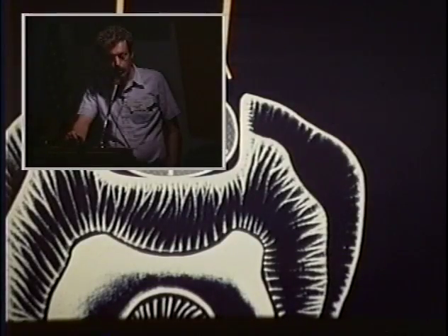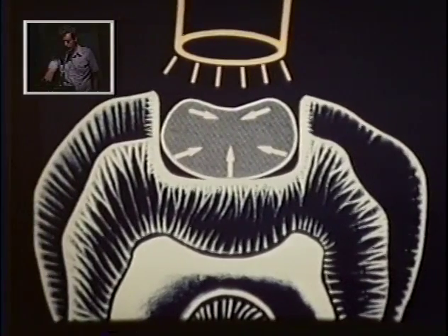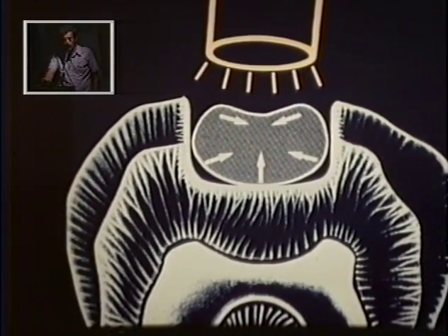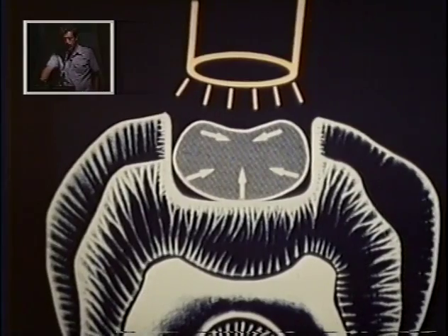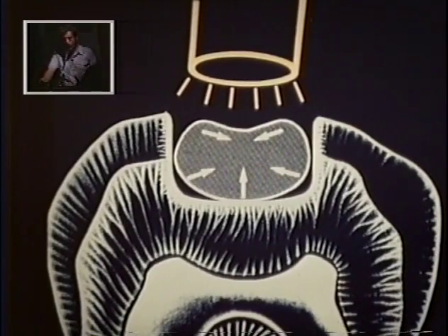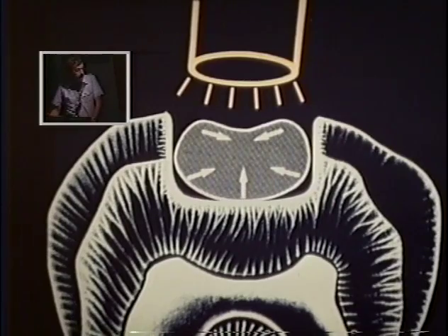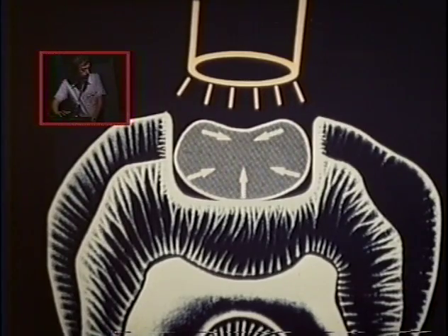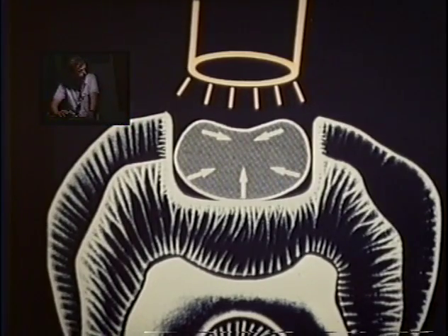And if you have the Gluma system, according to Bayer's directions, that's basically what you have. All right. Now, the only thing that'll save you is the instant bond, the instant grip. And then what you need is elastic stretching of the composite to hold it in contact with the tooth. Now, that will occur to some reasonable degree on some systems, as long as the bond strength is there. But it's an inherent problem we have. We've got the composite shrinking away from the prep, and we really ideally should reverse that.